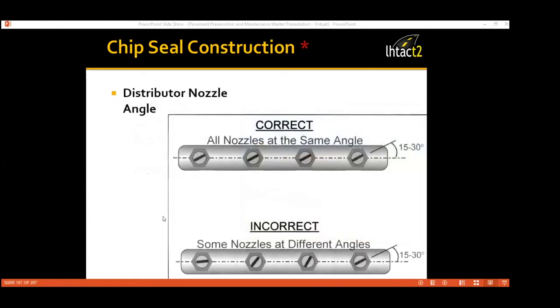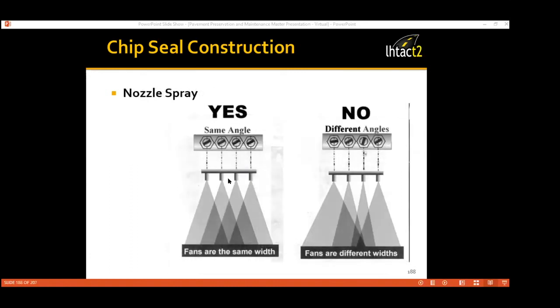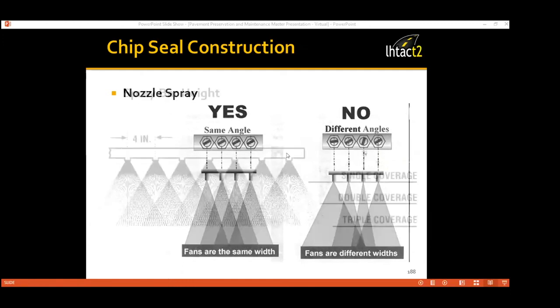So, the distributor nozzle angle: you certainly want them all to be at the same angle, anywhere between 15 and 30 degrees. You can see in the bottom picture it's incorrect because you've got nozzles that are out of kilter. They're not all uniform in the way they're angled. So you want to check that before you put oil down. When you get the same angle spray, the fans are all the same width, and you get a good application of oil. Here, you'll get different widths and in the middle you'll get some streaking, and it'll cause you a little bit of grief as far as how your chip seal turns out.